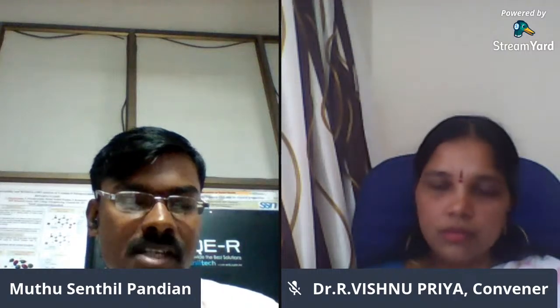But in the case of the SR method, what we have done is we have maintained a uniform temperature. We have maintained two different temperatures, top and bottom portion. So we have controlled the temperature. We have optimized the temperature. So uniform solvent evaporation, uniform supersaturation, uniform growth rate. There will not be any micro cracks in the SR method grown crystal. There is no milky opaque region. There are no solvent infiltrations in the SR method grown crystal. So the physical properties of the SR grown crystal are superior compared to the normal conventional method grown crystals.